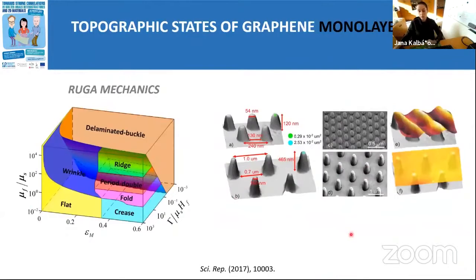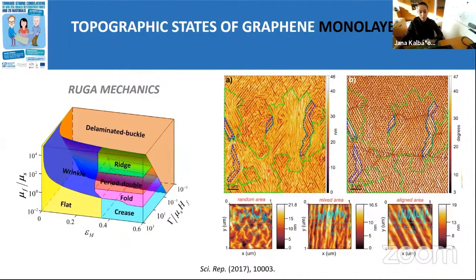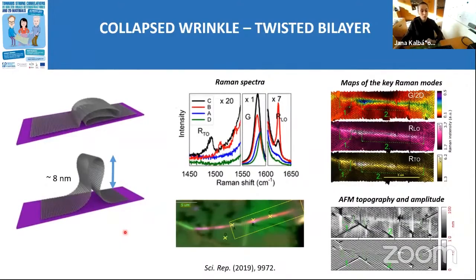I'm not going to discuss in detail what happens if we place graphene on such pillars. Essentially, it works in the same way, just by changing the parameters of the substrate. So it means the pillar dimensions, and also their distribution on the substrate. We can create many different states. But when we looked more into the detail in some of the samples, we observed some quite unusual features. So I will directly skip to the slide here, but I would like to show you what happens. Sometimes if we create wrinkles, it can make some kind of collapsed state. And the collapsed state is stable as long as the height of the wrinkle is about 8 nanometers. If it exceeds that height, it just makes a kind of wall.